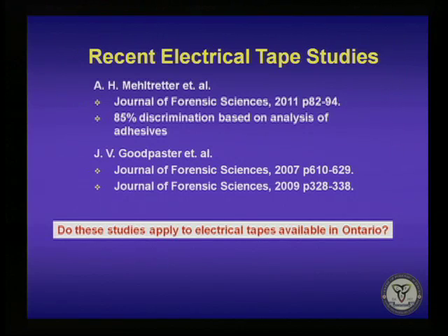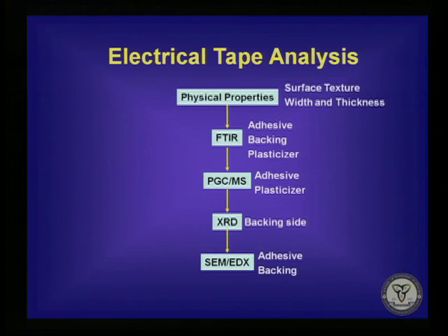One of the questions is, are studies done in other countries relevant to the tapes that we have available to us in Ontario? The way we do our electrical tape analysis is we start with the physical properties. We'll do microscopy, we'll look at surface texture, we'll measure width and thickness. We do FTIR on the adhesives and backings, and we extract the plasticizers from the adhesives using a solvent, and we'll analyze that as well. We look at the adhesives and plasticizers using PGC-MS. For this study, we didn't look at the backings, but we would in casework. We did XRD of the backing side of the tapes, and we looked at SEM EDX of both the adhesive and the backing. In casework, we would look at physical properties first. In our case, due to the large number of comparisons, we looked at physical properties last.